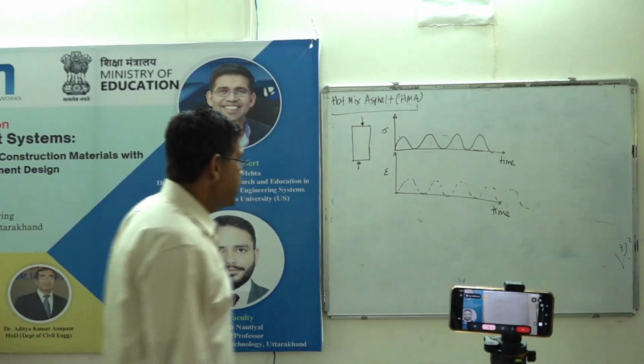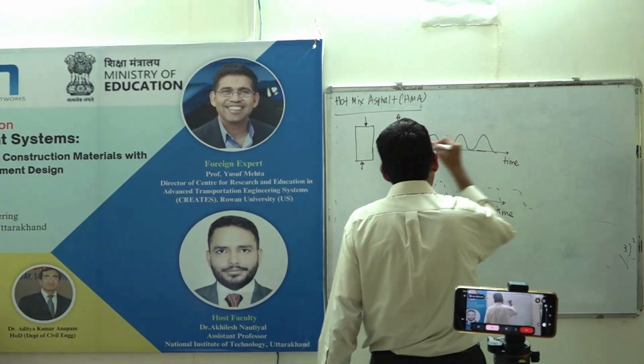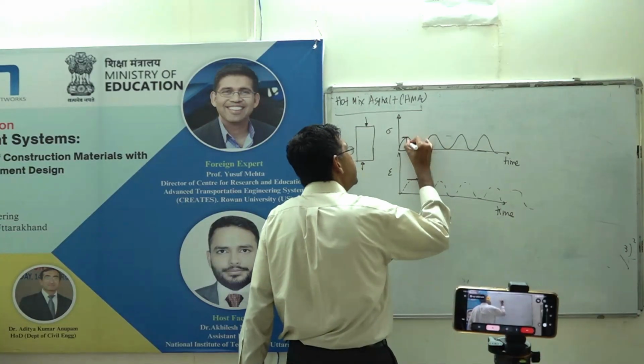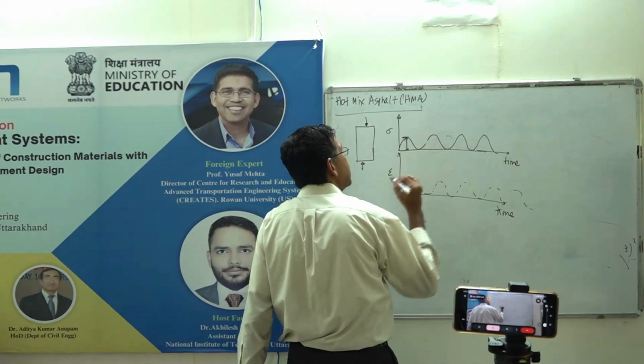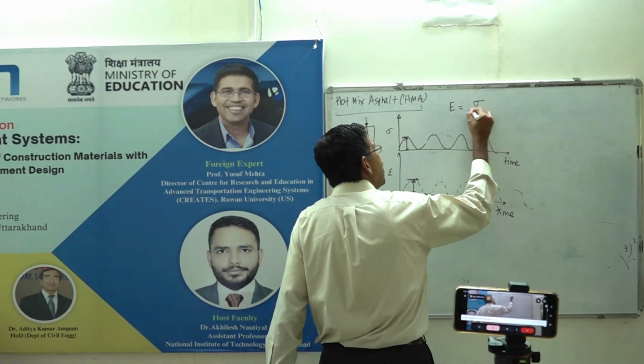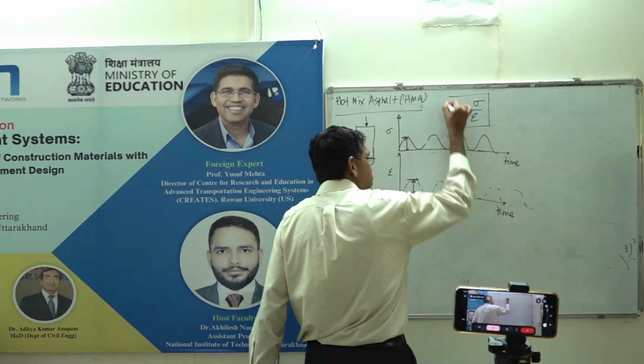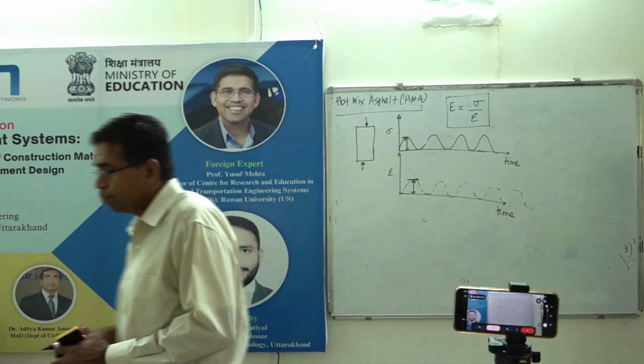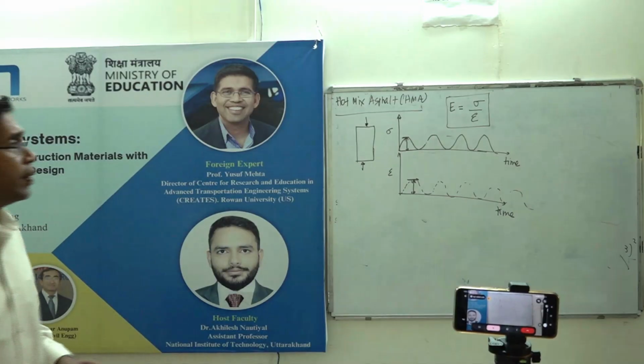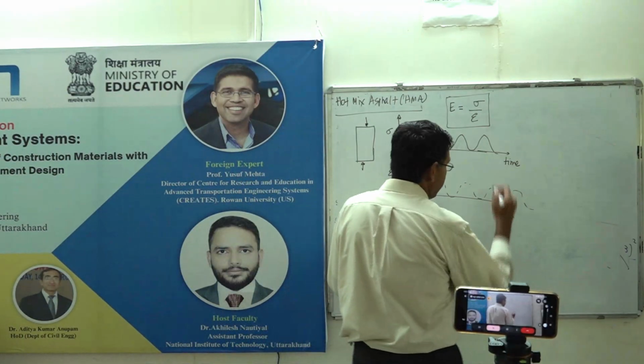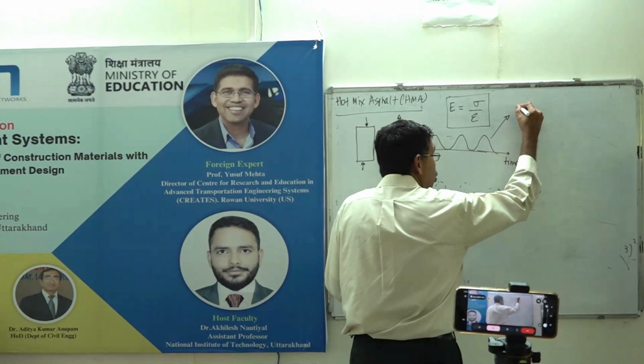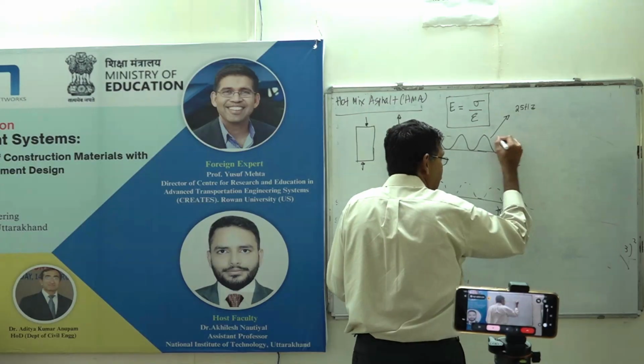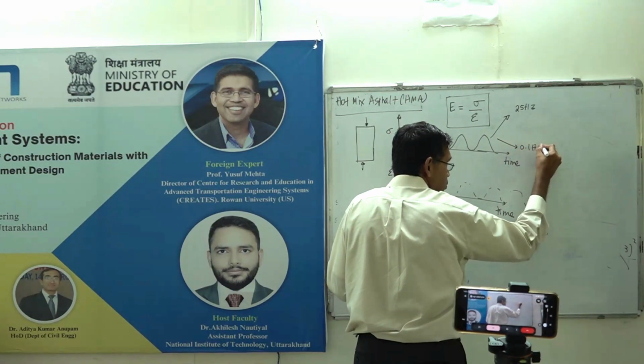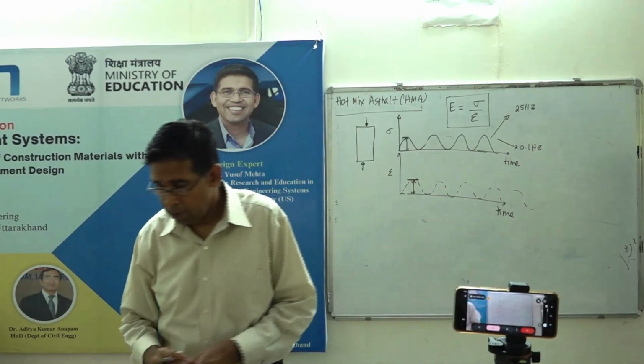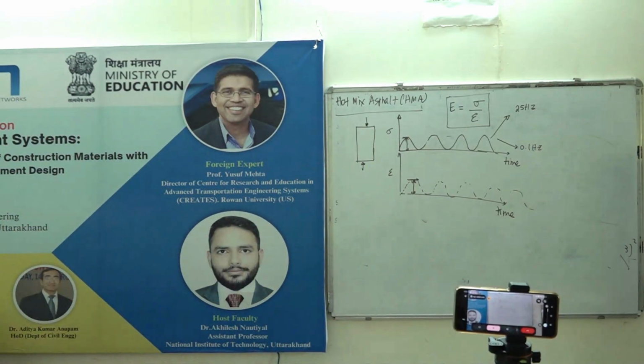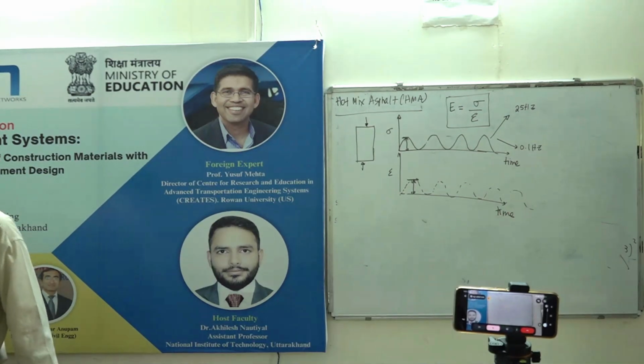So what you will see is the dynamic modulus is given at any point by sigma over epsilon, right? So E star is given by sigma over epsilon, stress over strain. That's your dynamic modulus. What happens is you run this at different frequencies. So this can be run very fast, all the way to 25 hertz, and as slow as 0.1 hertz. Different frequencies, right? And it can be run at different temperatures: 12 Fahrenheit, 40 Fahrenheit, 70 Fahrenheit, 100 Fahrenheit, 135.